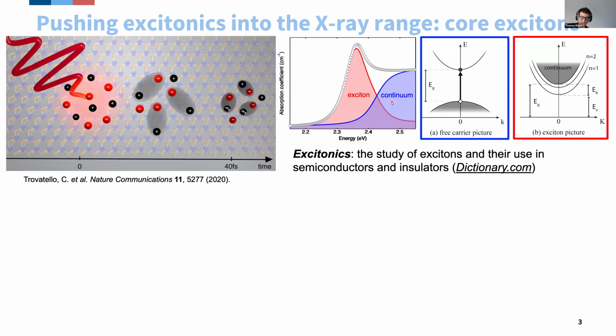descriptions to be able to interpret optical absorption in a semiconductor. One is based on the continuum of absorption. That's what you get when the photon is absorbed and promotes an electron from the top of the valence band to the bottom of the conduction band, but these 2 particles are not coulombically bound together. They are called free carriers. The excitons, however, form below the bandgap with an energy that corresponds to the binding energy. So it forms at a lower level than the bandgap by an energy that corresponds to the binding energy of this exciton. And yeah, excitons in the optical range are very popular quasi-particles.